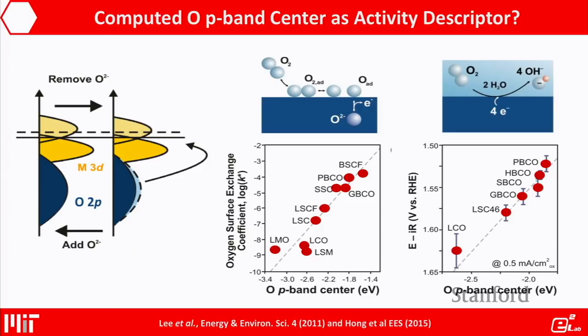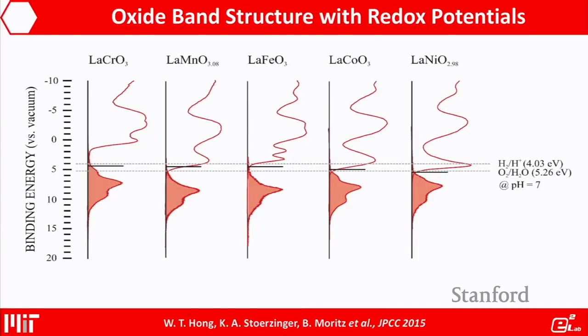We all know that correlation is not causation. So what is the physical origin that influences this trend, that increasing metal-oxygen covalency increases the catalytic activity? Unlike metal surfaces, where over the past few decades there have been a large number of measurements and computations of the electronic structure, when we started this project 10 years ago there were actually very few measurements of the density of states for metal oxides. So we collaborated with Wanli Yang at the ALS and utilized X-ray emission spectroscopy and also X-ray absorption spectroscopy to map out the density of states for these perovskites.